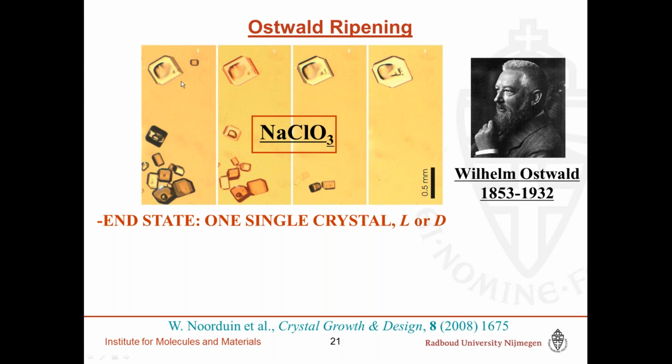So the thermodynamically most stable state is the one on the right hand side, where you have a saturated solution in equilibrium with one crystal with a shape which also is dependent on the interfacial energies of the different facets on this crystal. So also the shape has one particular shape, which is the equilibrium shape in contact with this saturated solution. So this is the equilibrium situation, and this is indeed stable.